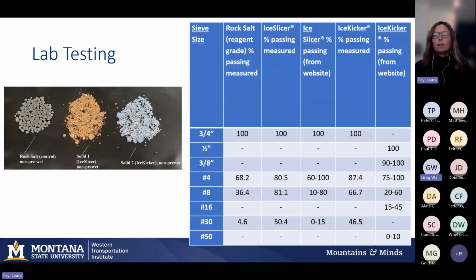So for the reagent grade rock salt, you have a pretty uniform distribution of large, medium, and small, with note that there's a very small percentage of fines though. With the ice slicer, initially, again, we pulled that from the website, and so there are ranges reported, so that's the fourth column over. But then we measured it after the fact, and this is something we would take back if we could, but this is how it was done.